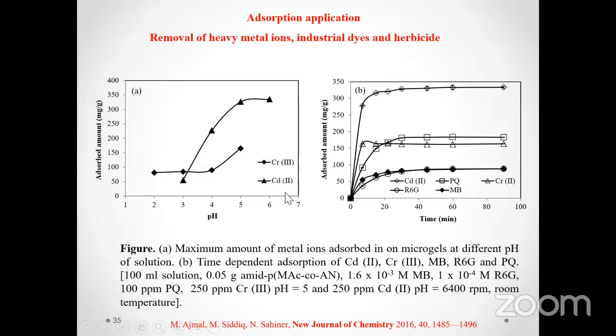However, as is obvious, metal ions can form complexes with the change in pH of the medium. So it was observed that when we increase the pH, complexation of the metal ions was also observed. So below that pH, we have observed their adsorption, and in the case of cadmium, the maximum adsorption was at pH 6, and that of chromium was observed at pH 5. Above this pH, these metal ions were converted into metal complexes, and they would get precipitated in the reaction medium. And their adsorption capacity was as high as more than 300 milligram per gram of the hydrogels for paraquat in this case.